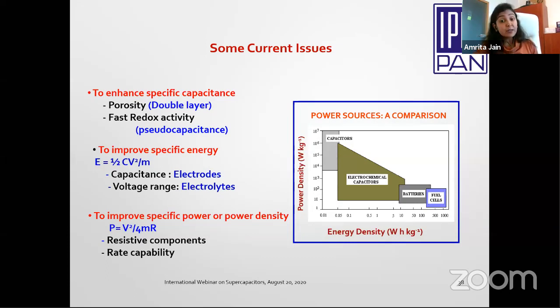To improve the specific power, the formula to calculate the specific power is P equals V square by 4mR. m is the loading mass of the electrode, R is the resistance. So what we should do to increase this power is to have less resistive components, and of course the rate capability should be higher, and certainly again the voltage. You see, to increase the specific energy and power density, we need a good electrolyte with good potential difference, but with good potential range. Its potential window should be good.